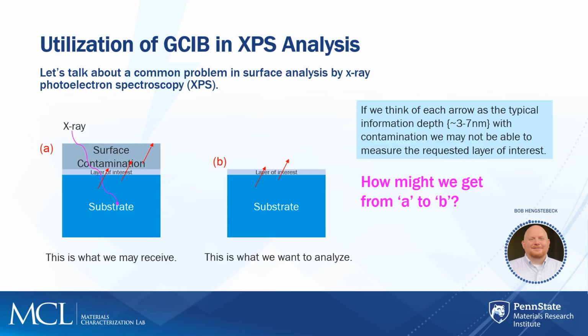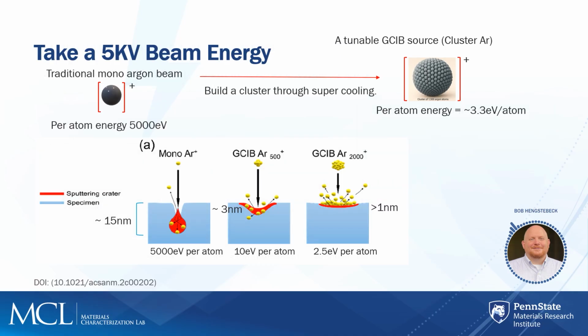And so this GCIB is turning out to be a new method for doing this, and a pretty good one. But let me get into why that would be. So one of the ways that we can go about cleaning our surfaces is using an ion gun. And this is typically something that people have used for many, many years. But the traditional ion source is a monoatomic source. And what that really means is we're going to take a single atom or molecule, so maybe in this case argon, or in the case of oxygen, O2, and we're going to ionize that species, and we're then going to bombard it onto the surface.